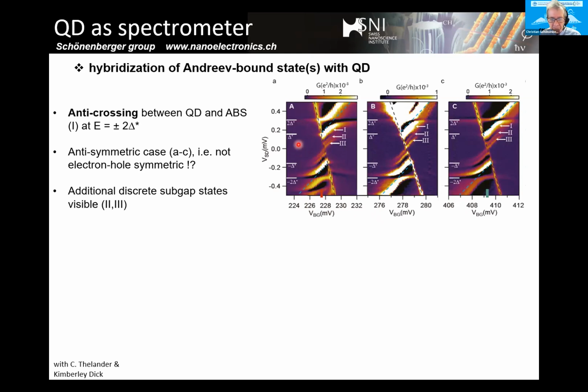Then you see something featured around delta, but now you also see a feature at 2 delta, and that's because with superconductor to superconductor, the quasi-particle onset would be at 2 delta and minus 2 delta. So that already shows that there is another contact. We now have 2 superconducting contacts. There is this line going through, and then there seems to be an Andreev bound state coming in here, which has an anti-crossing with the dot state. You see this anti-crossing feature very strongly, and there's some feature inside the gap which has to do with the softness of the gap. It's an intriguing, nice picture here, and this is going to change when we change the gate voltage.